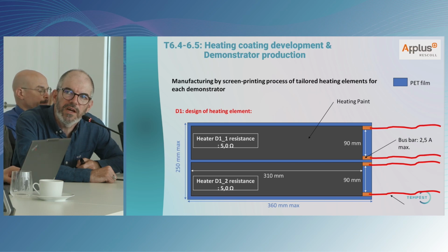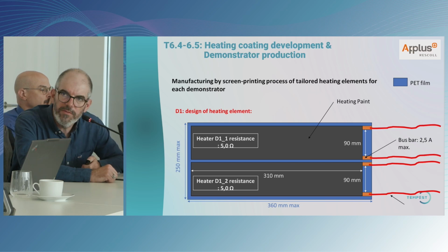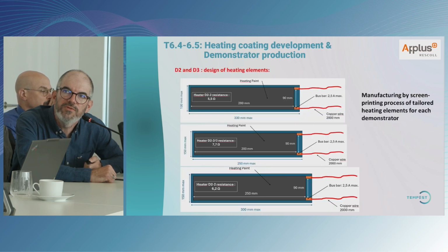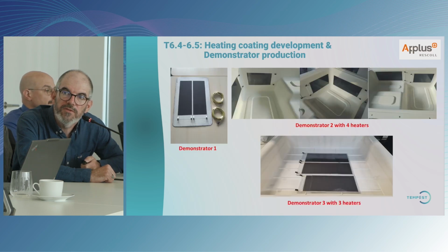The paint is applied by screen printing on the base liner, and then on the opposite side, facing the housing, there is a pressure-sensitive adhesive. So my colleagues prepared different sets based on the design, D1, D2, and D3, and as I said, the manufacturing was done by screen printing. And then you see these heating patches deposited on different locations of the different demonstrators.